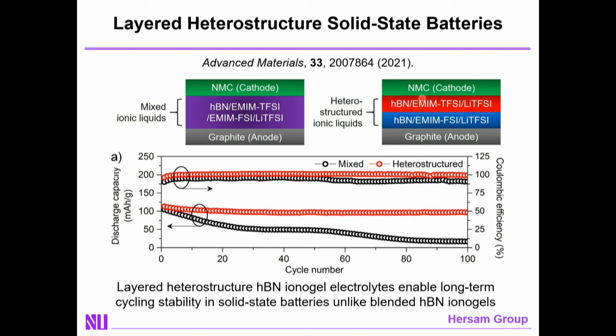In the heterolayered case, we see exceptionally high cycling stability, whereas if I were to just blend the two ionic liquids together, they would both touch both of the electrodes. They would both undergo a degradation upon cycling, and as a result, you see in that case in black, very fast capacity fade. So this looks quite promising.